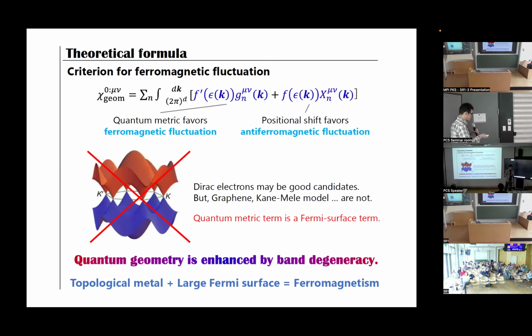But I'd like to mention that the canonical Dirac electron systems, such as graphene or Kane-Mele model, are not suitable for our purpose because, according to these terms, the quantum metric term is a Fermi surface term. So in the absence of the Fermi surface, the contribution from quantum metric disappears. So from these results, we expect that the topological metal with large Fermi surfaces may be a platform of ferromagnetic fluctuations induced by the quantum geometries.